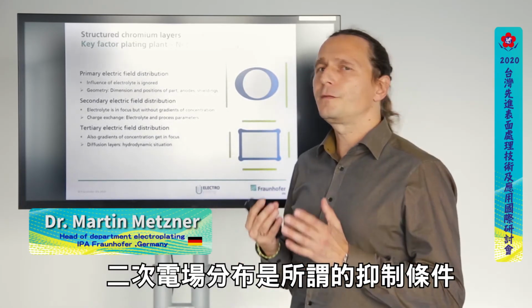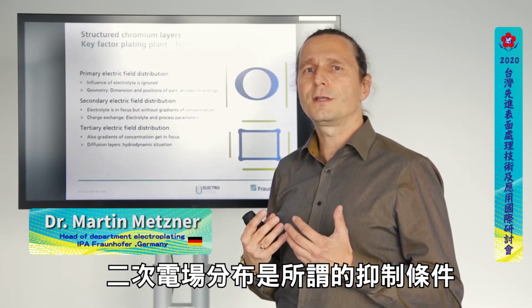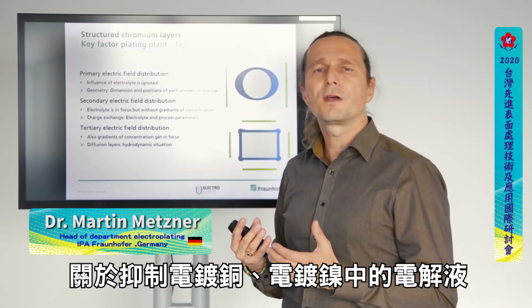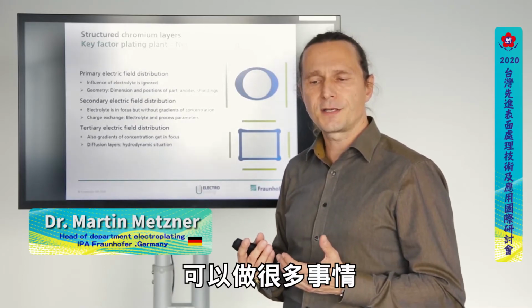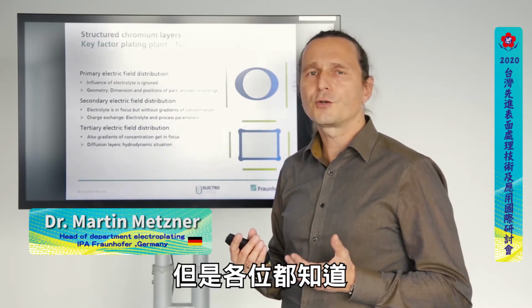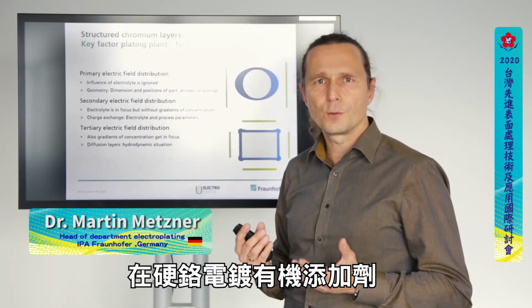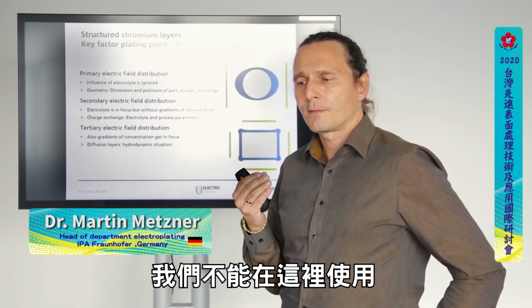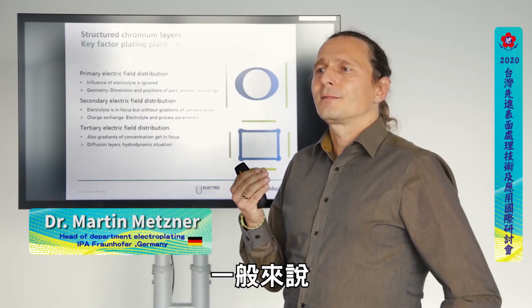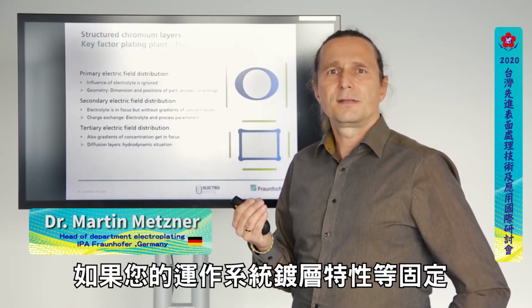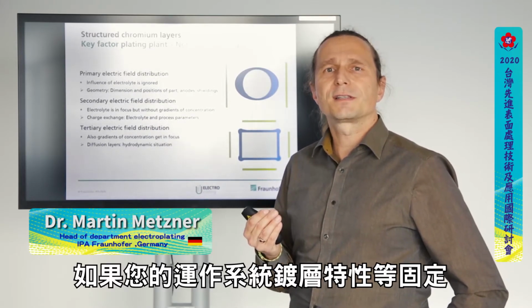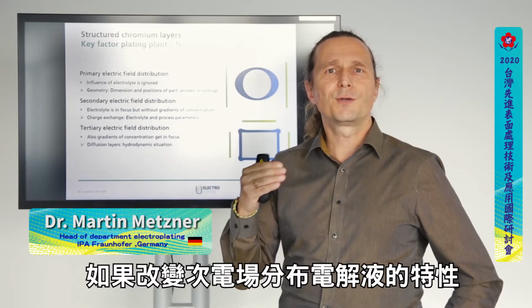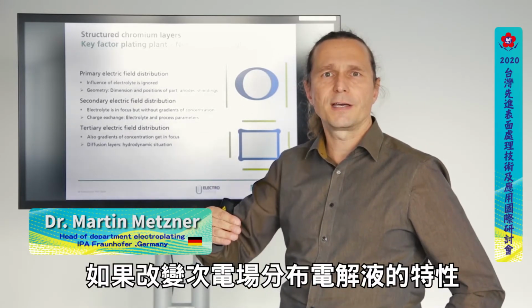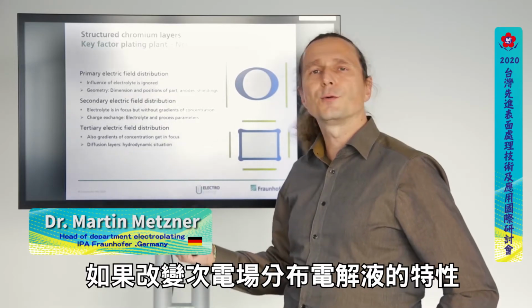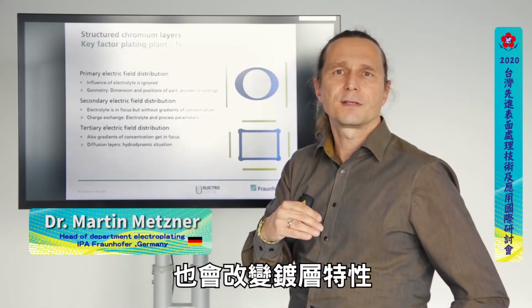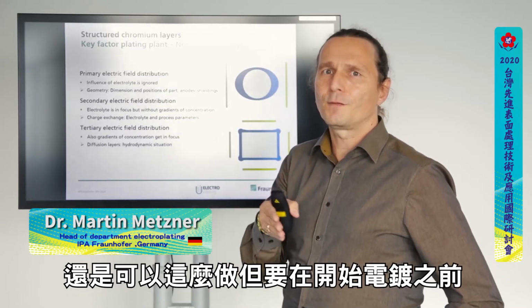The secondary electric field distribution, this is everything what we call inhibition. We can do a lot concerning the inhibition of the electrolyte in copper plating and nickel plating. But all of you that are in hard chromium plating know that organic additives do not work in hard chromium electrolytes. We cannot use them in here. And generally spoken, when you've got a running system with fixed layer characteristics and everything, then you cannot work with that, because when you change the characteristic of the electrolyte concerning the secondary electric field distribution, then you also change the layer characteristics. So you can do this, but before you start plating.